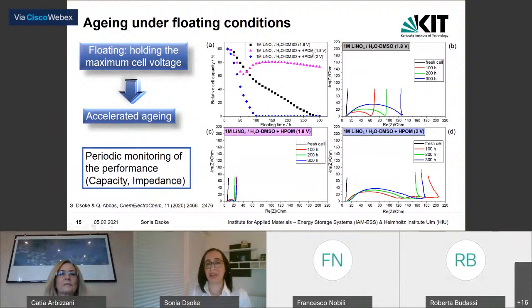When we keep the cell at the same voltage and we add the polyoxometalate, we observe at the beginning one decrease and then a stabilization. And this is also reflected by the impedance, which shows an initial increase, but then remains constant for the whole period of the experiment. Unfortunately, by pushing the cell voltage to 2 volts in the system containing the polyoxometalate, we observe a rapid decrease. And after 100 hours, the system cannot deliver any capacity anymore. And we also observe a huge increase in resistance.